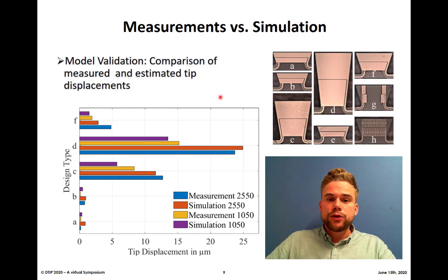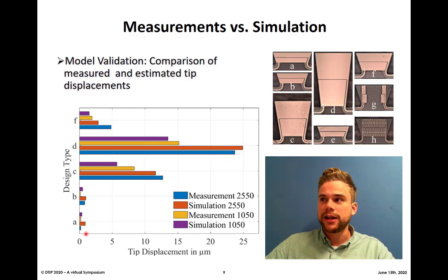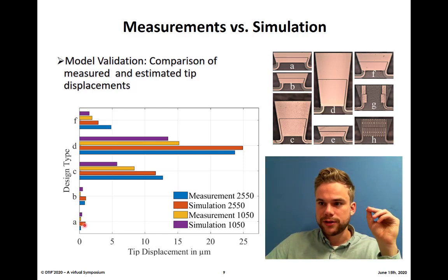So now a small slide about the measurement versus simulations, where we see that we have predicted the displacement quite well for highly elongated flappers. For case D, for instance, that would be that one here, highest spatial length, unfortunately we did not match it perfectly, but it's just a deviation of 5%, so this is okay so far. But for case A, on the other hand, which is a very small flapper, we get an error of 280 something percent. See, the measurement and simulation results are varying severely.